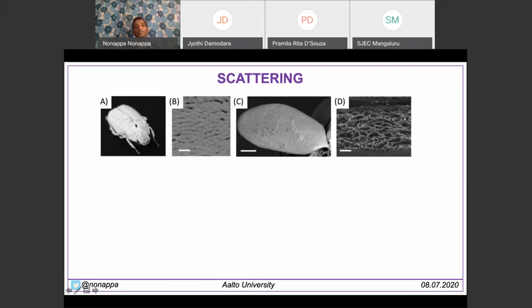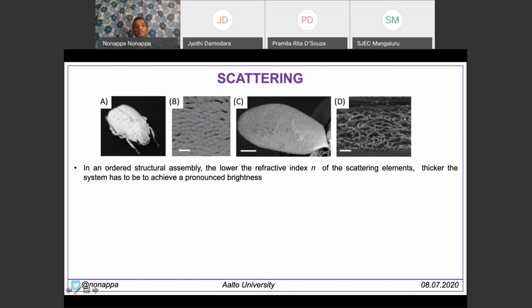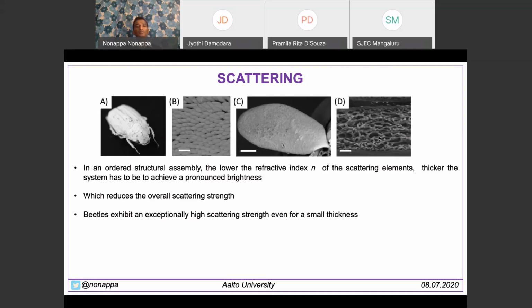And another important phenomenon for why you can see white coloration is that if you take the scanning electron microscopy of this structure, you see highly anisotropic, meaning not spherical, structures. These are small structures, and if you look even further, you see a highly disordered structure. The disordered structures are the ones responsible for such bright white coloration.